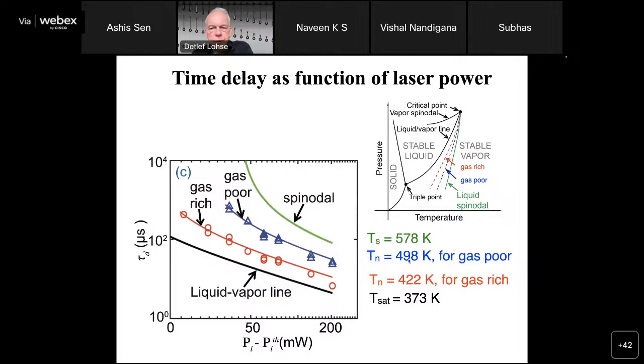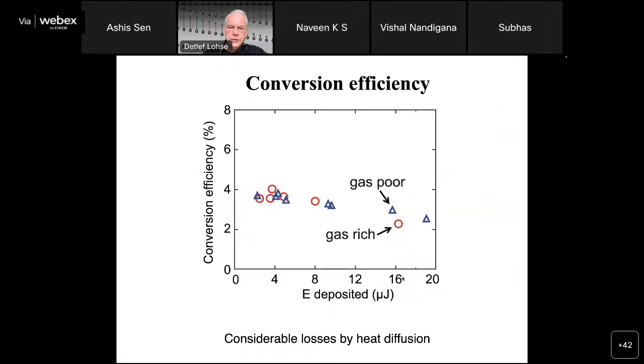So for the gas-poor case, we achieve 500 degrees, so nearly the spinodal temperature, whereas when there are many air pockets in there, nucleation is earlier, and the nucleation temperature is only about 420 Kelvin. So when we calculate the conversion efficiency, in fact, it's very poor. It's about 4%, whether it's gas rich or gas poor, and it's not very efficient.